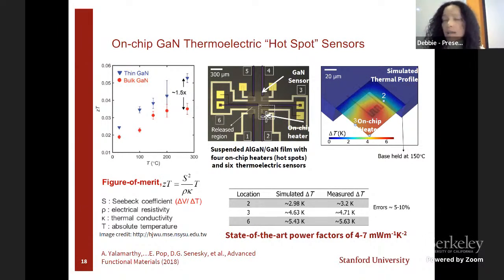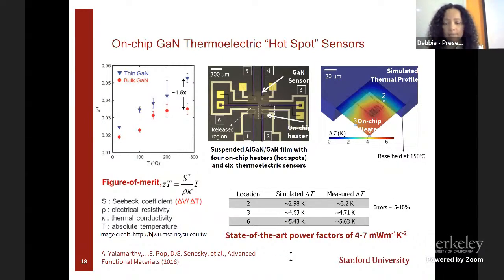We tested this out using MEMS fabrication techniques, where we created this suspended AlGaN-GaN membrane here. We machined these platinum heaters, so we created a hotspot across these purple two-dimensional electron gas thermoelectric structures. This is the hot side, and then the substrate, the unreleased portion, is the cold side. And then we can model it, see what the delta T is, and oh no, battery's running low.